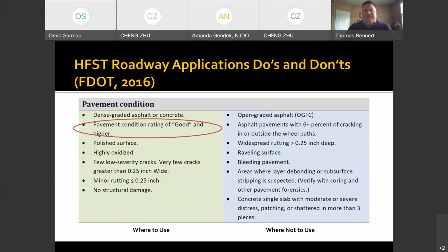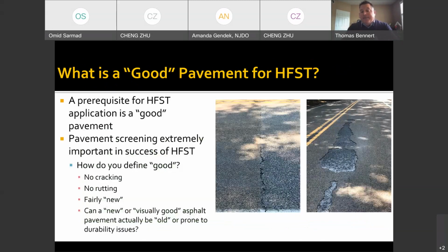And I have here highlighted pavement conditions rating in good, and I'll explain that in a minute. Areas where there are some examples of polished surface, very low severity cracking, et cetera. The big thing here, though, is that there is a recommendation for a good pavement. And the problem is what defines good. And so when we're talking about selecting or pre-screening pavements, in general, we think of good as no cracking, no rutting. But can we actually have a pavement that appears to be in good condition, at least from a visual perspective, but not be a candidate for HFST?